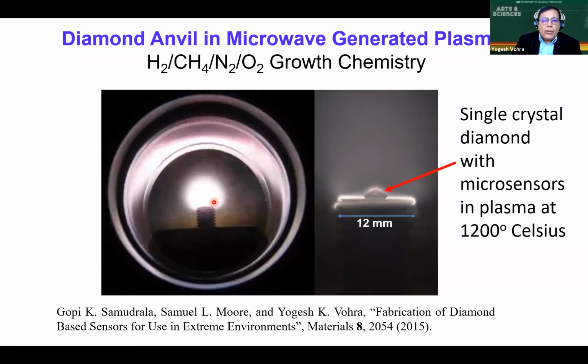experiments. So this is a shot of the plasma which is created in the chamber, and you see here down below is a molybdenum substrate, and here is an example of actually a diamond crystal sitting in a plasma. Okay, so typical temperatures are a lot higher than what you see here. In growth it is about 1200 degrees Celsius. So this has been viewed through a filter, so you can actually see the diamond clearly.